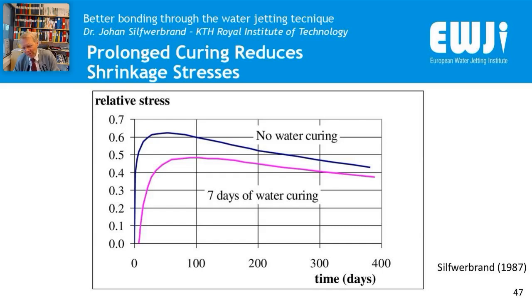And the reason is that if you cure your concrete properly, you are also promoting the development of tensile strength, and then you will have more tensile strength when the concrete starts to shrink, and it doesn't start to shrink before you have closed your curing. So this is a theoretical slide, but it shows the importance.